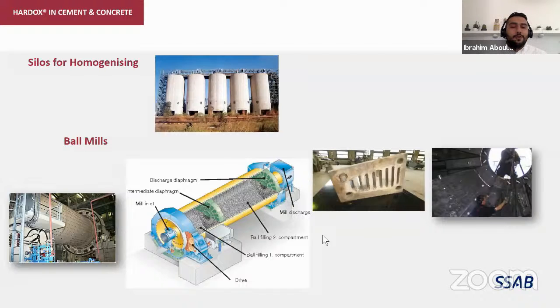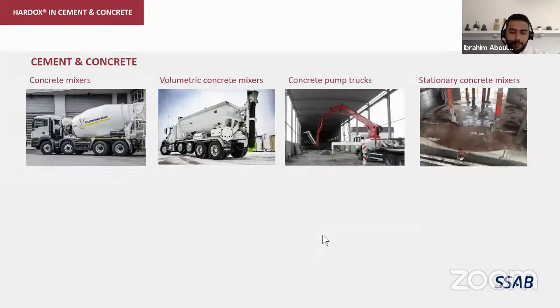Since there is more or less no impact on them. They are quite in a different direction than where the impact is happening. They only pass the ground material to the next section. For that, it's only sliding, and Hardox 600 has proven a lot of success in that. So you have at least 15% more service life than castings in the diaphragm, 15%. And that's quite huge for the ball mills.